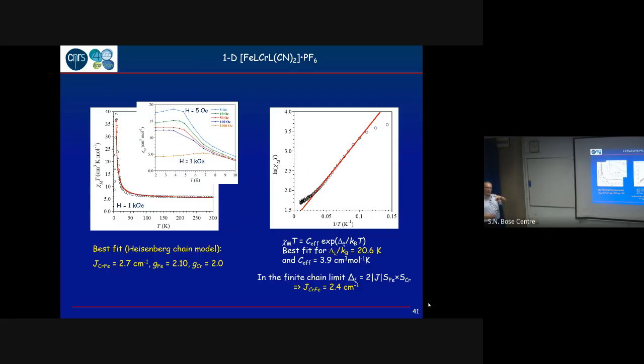So you have been asking about the intermolecular interaction or not. In this plot here, what I show is the susceptibility versus temperature, and you see here the plots when reducing the applied field. And what you can see is that in this system, we don't have interchain interactions. Because if we would have, let's say, antiferromagnetic interaction between the chains, when you reduce the field, this should come down. And it doesn't come down because there is no antiferromagnetic interaction.